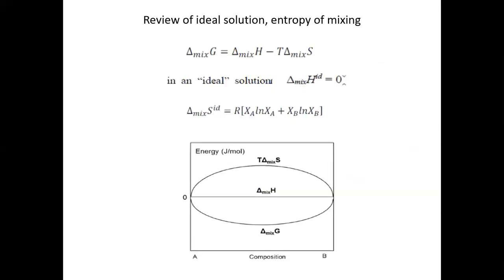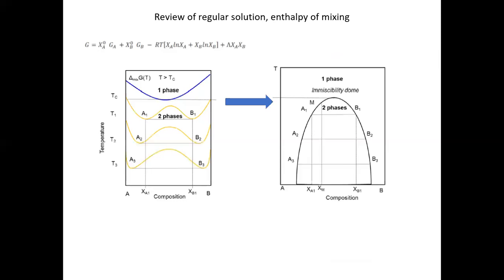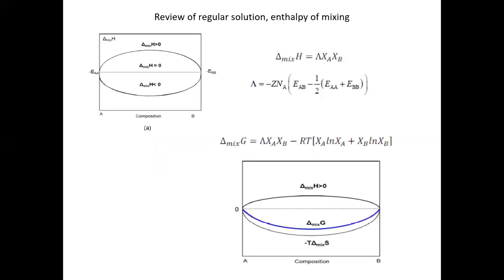And we also discussed why you have curves like this, why the free energy wants to develop a local minimum as you lower the temperature. One classic and very useful model to understand this phenomenon is the regular solution model. You have a competition between the enthalpy of mixing and the entropy of mixing. The entropy of mixing always favors the mixing state, because mixing increases entropy, which contributes a negative term to the free energy. So increasing entropy always reduces the free energy, and the higher the temperature is, the larger this contribution is.